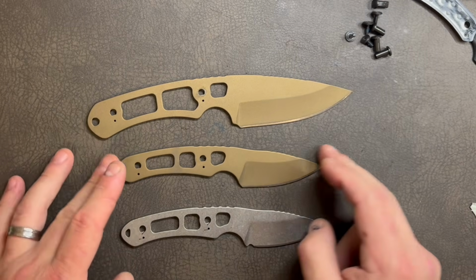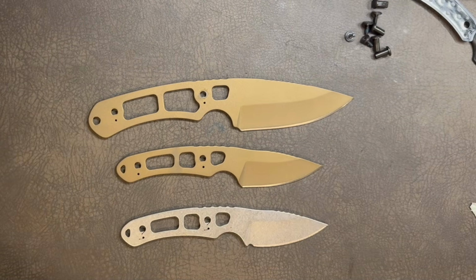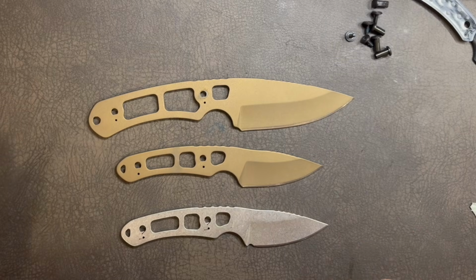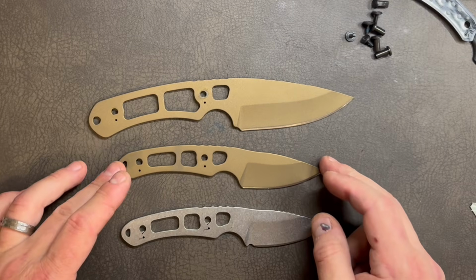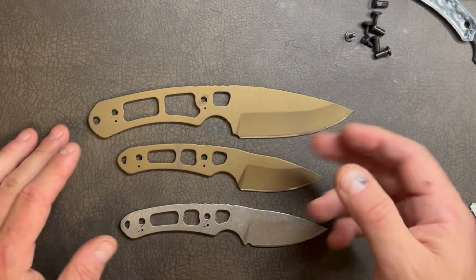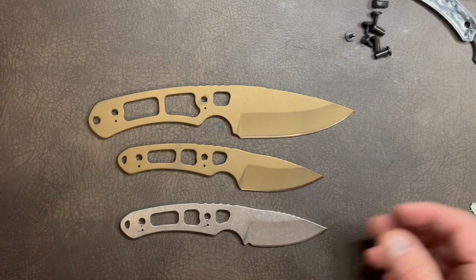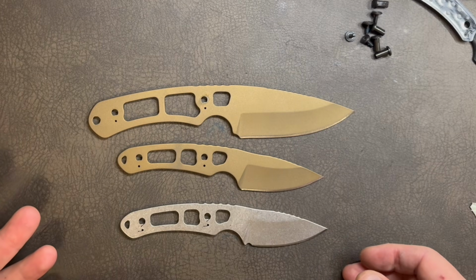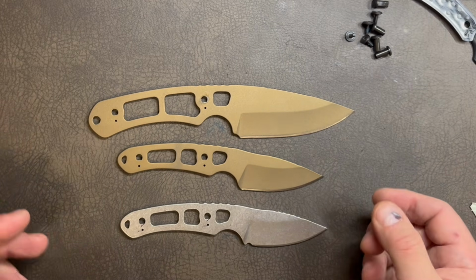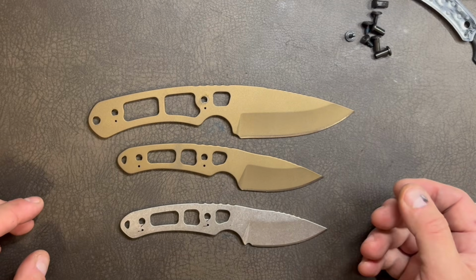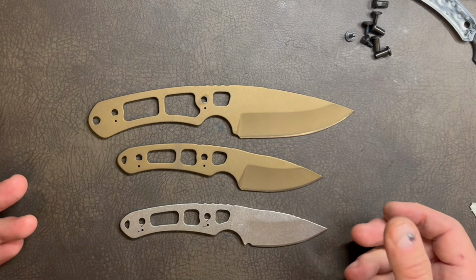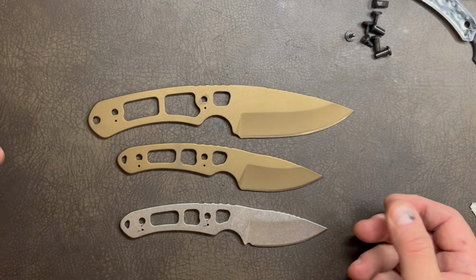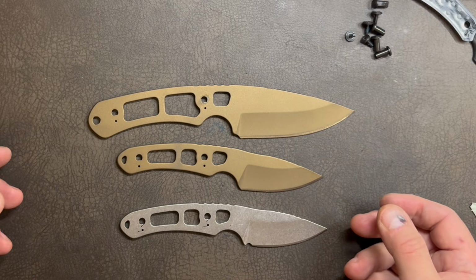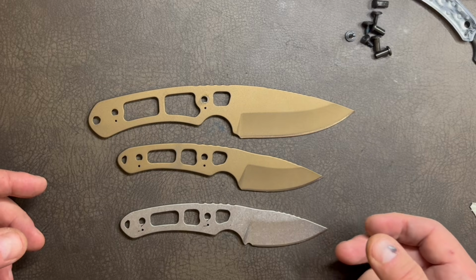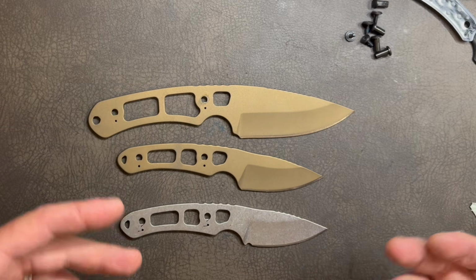Now, you know me, I'm not a big proponent of coatings, but not because of these minor things, rather because it's really easy to mess up the heat treatment, because most of the blades are coated after they went through the full heat treat cycle, reached the desired hardness, and then with the Cerakote as an example, you end up sticking it into a chamber that is heated up to 250 to 350 Fahrenheit for a couple of hours, and that can actually act as a post-heat treatment tempering.